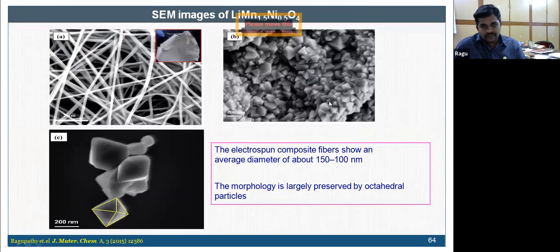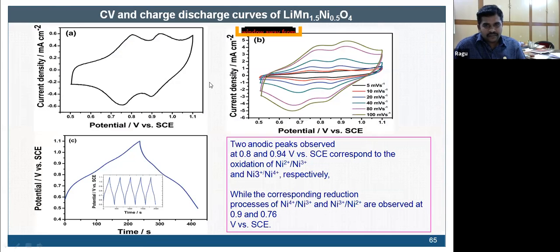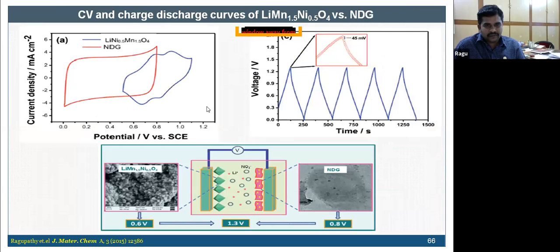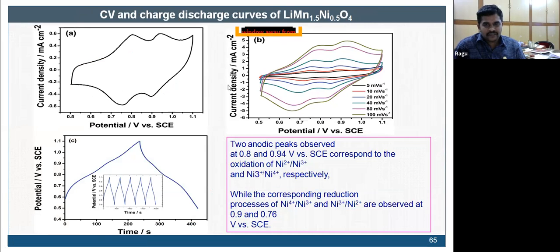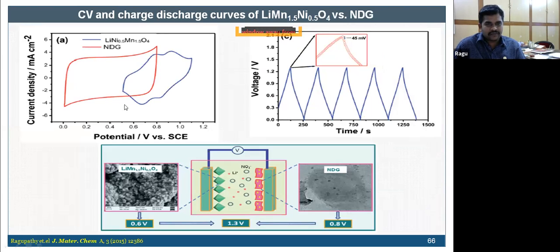Okay. Look at this. This is the SEM image, that is scanning electron microscope image of the active material. Don't worry about that. And this is also a lithium ion supercapacitor. So here is the characterization of these compounds independently. Look at these. The red one is a supercapacitor material. The blue one is your battery material, right? You could see the redox behavior, and there is no redox behavior. When you operate these two components independently, you could see that it is only 0.8 volt in the case of supercapacitor material. When you use battery material, it is only 0.6 volt.